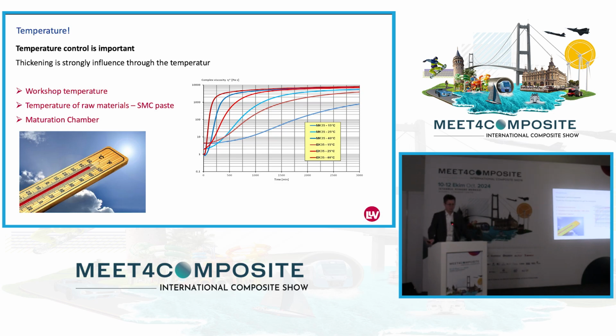Most important, and that's why we normally like the fall season, because the temperature is always at the same level, is the temperature. During your process, in your workshop, from the resin to the additives. The most frequent remark about changing thickening is because of the temperature. Here again, viscosity and time. This time you can see the scale is not equal, it's 1, 10, 100, 1000. And you can see here, for example, the MK35 at 15 degrees, 25, and 40 degrees. Only a temperature difference of about 10 degrees already makes it close to 100 times faster in thickening. So control of the temperature is the most important part we can recommend.